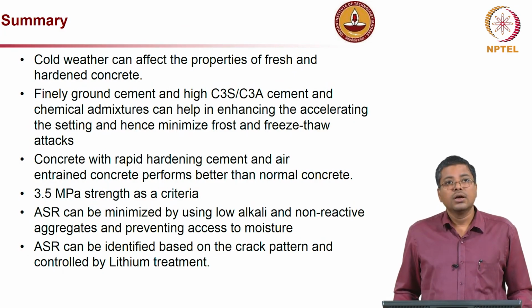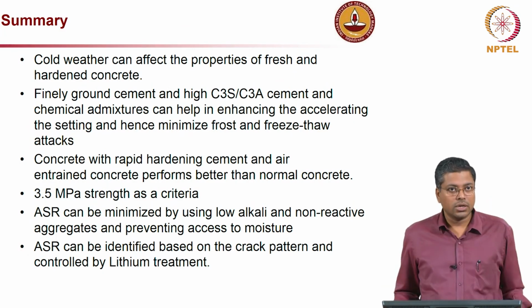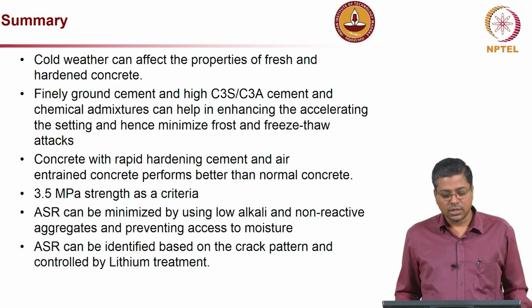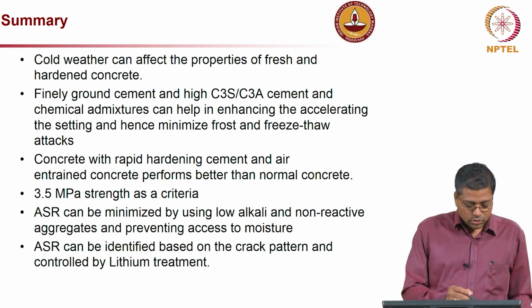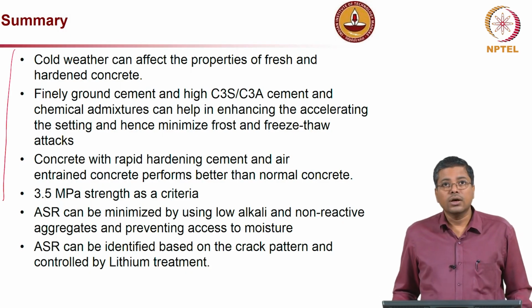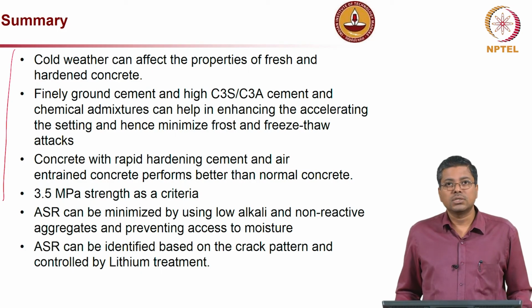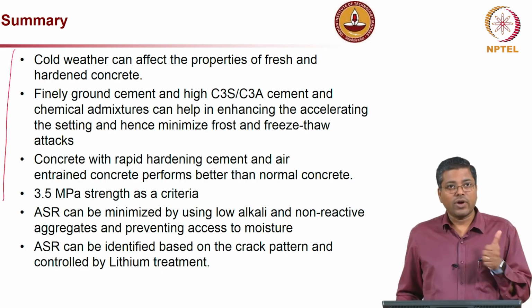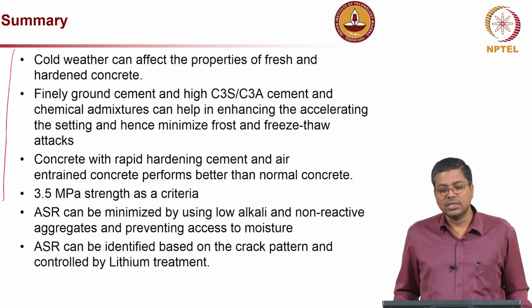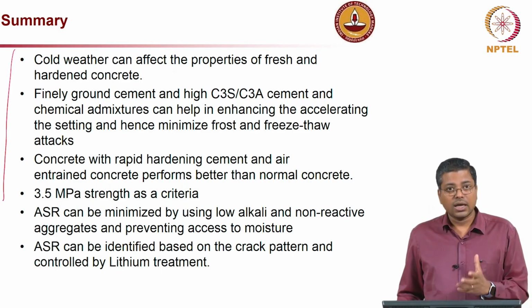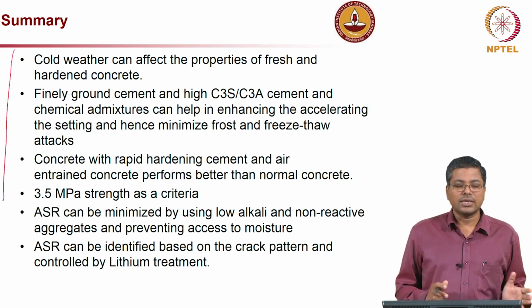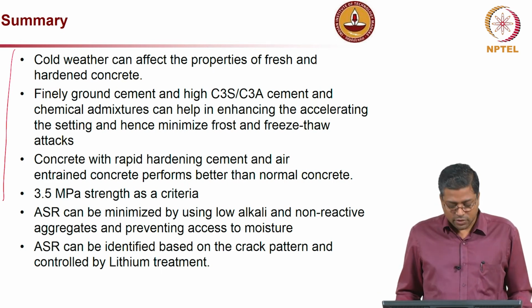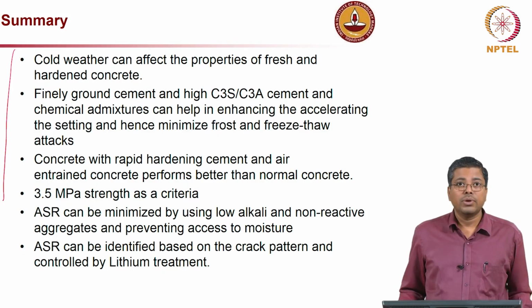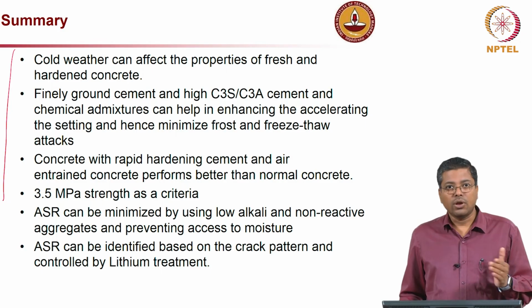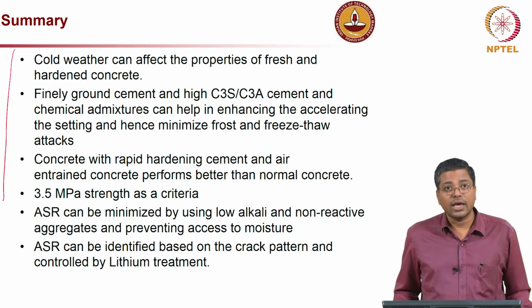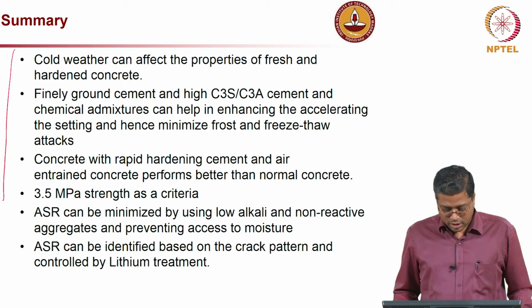For summarizing, we looked at both cold weather concreting and associated issues, and ASR. In cold weather, we were talking about how cold weather can affect the properties of fresh and hardened concrete, and how finely ground cement and cement with high C3S or C3A content, and chemical admixtures, either an accelerator or an anti-freezing chemical, can help in enhancing the setting time. And also, I do not have it written here, but air entraining admixtures can also help.